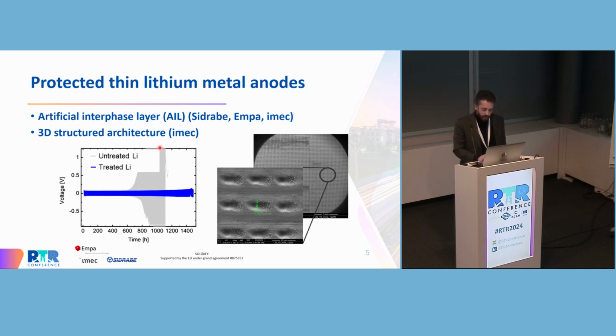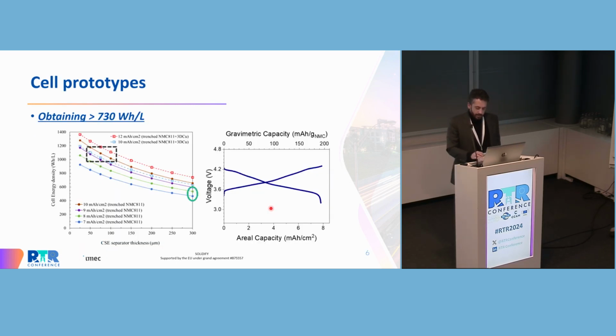Another aspect which we have explored is the optimization of a 3D structure current collector to decrease the local current density in the cell. And this improvement at component level led to an improvement in terms of cell prototype. So at the moment we are working between the coin cell and the monolayer pouch cell, and we can get an areal capacity of 8 milliamp-hours per centimeter square, which corresponds to an energy density of slightly above 700 watt-hour per liter.